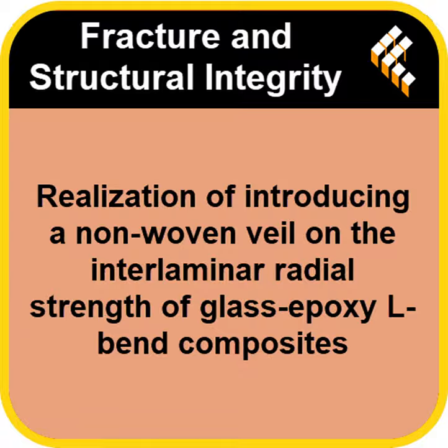Right, because that specific combination provided enough reinforcement to make the crack path difficult, but it was sparse enough to still allow flexibility and good bonding between the main layers. It forced that energy-absorbing, cohesive failure. So what, for anyone actually building things, is interleaving works, but you have to tune it. Stiff stuff needs to be used sparingly at the interface. More flexible stuff gives you more leeway on density, but the performance boost might be less dramatic. That's the practical design guideline coming out of this.